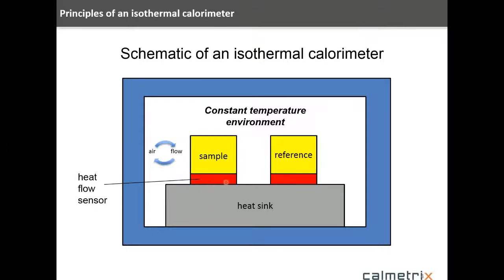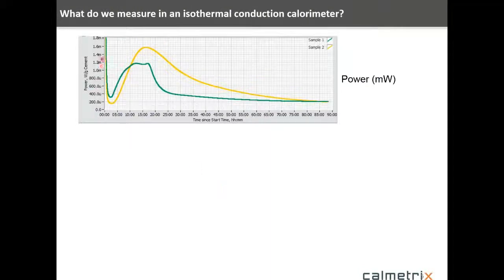The heat flow sensors, which are basically thermoelectric devices, measure that heat flow. The raw signal coming off these sensors is a voltage signal. And through the manufacturing process, when we calibrate the instrument, we relate that voltage to a heat flow in watts. So typically the data we're looking at then is watts. In most cases, we will normalize that per gram of sample. So we normally present it as power in watts per gram, as a function of time.